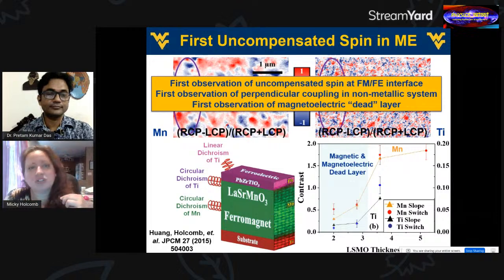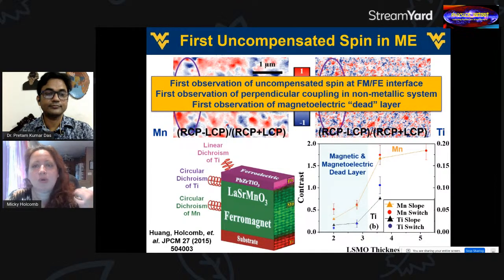We had a lot of cool firsts. So this was the first observation of uncompensated spin at the interface between a ferromagnet and a ferroelectric. We were able, with a lot of analysis, to actually compare the orientation of those uncompensated spins, their direction, compared with the magnet. And we found that it had a preference for perpendicular coupling. First time that's been seen in a non-metallic system. It does happen in some metallic systems. And also the first observation of a potential magnetoelectric dead layer.